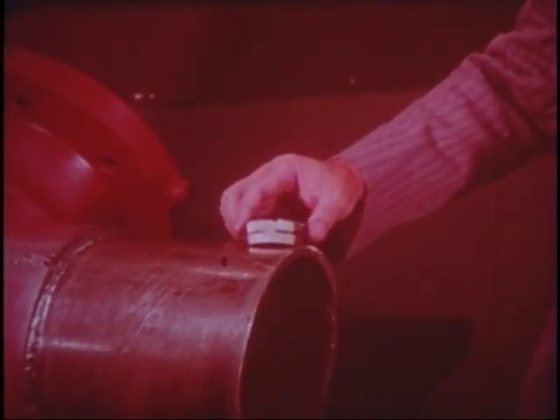This is an example of cracking in the heat-affected zone. This normally results from the absorption of atomic hydrogen from the molten weld metal into the heat-affected zone. Rapid cooling traps this hydrogen in the crystal lattice and builds up pressure. This pressure, combined with shrinkage and any hardening effect of the steel's chemistry, causes cracking.